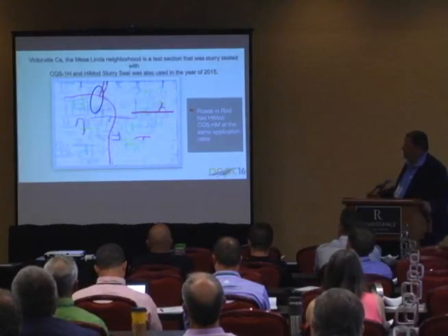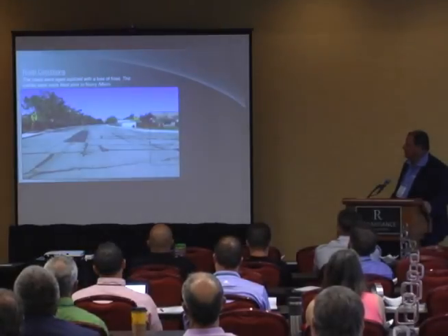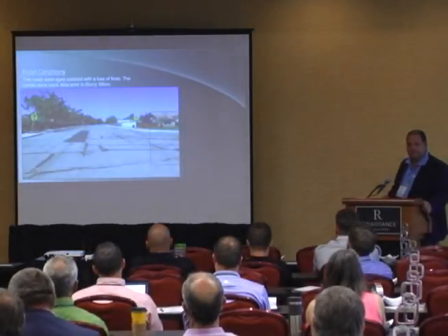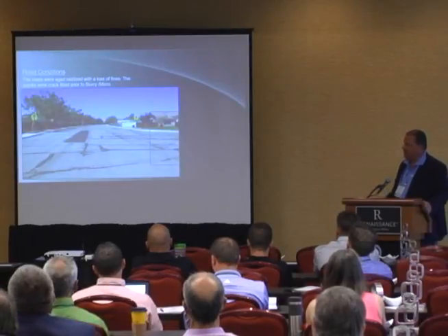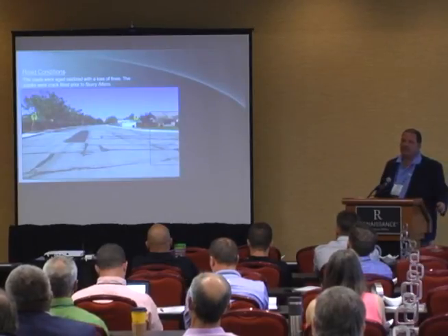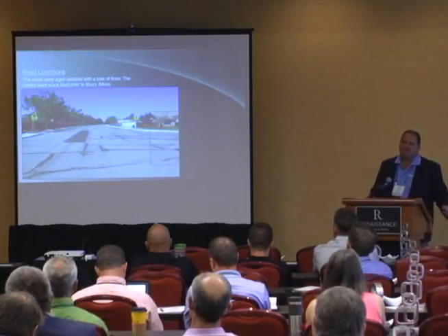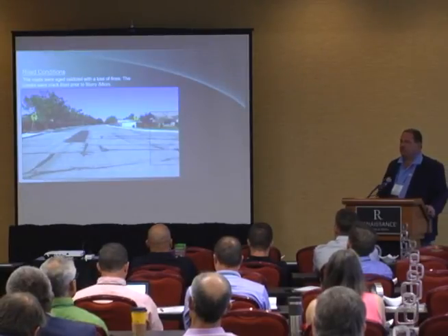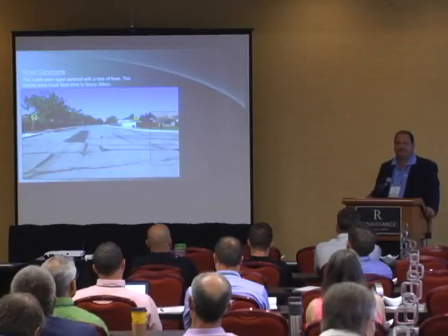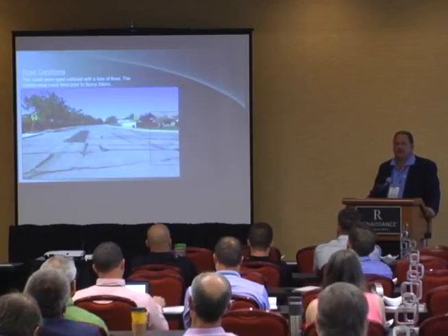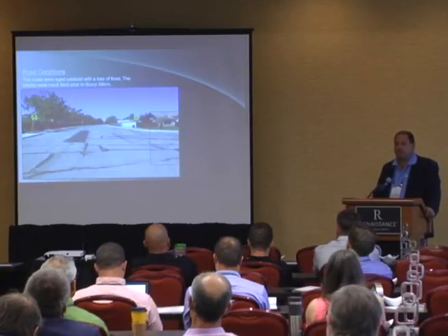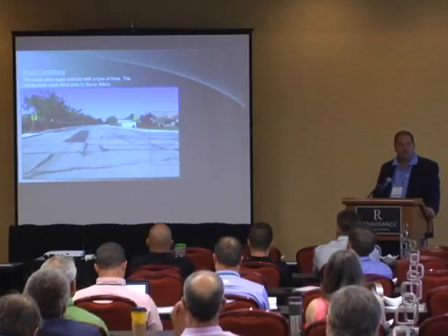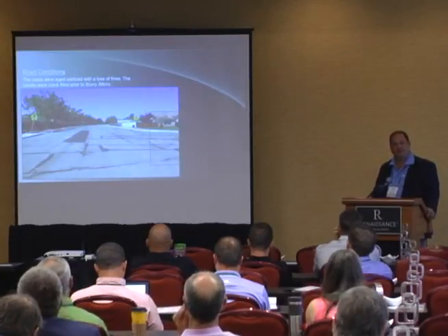Obviously, we do lots of projects comparing different products. This is just a project map showing comparisons, map cracking, checking out all the cracks, documenting, seeing what we have. This is up in Victorville, the high desert. We get a lot of freeze thaw. It wouldn't be unusual in Victorville in October to see temperatures of 98 to 100 degrees, and the next night it might be 32. So we get huge temperature swings, lots of thermal cracking, lots of moving up there.